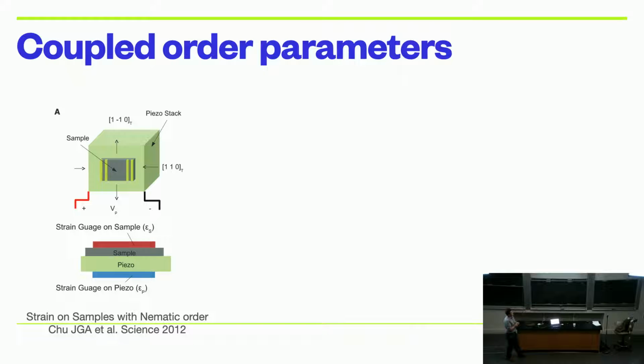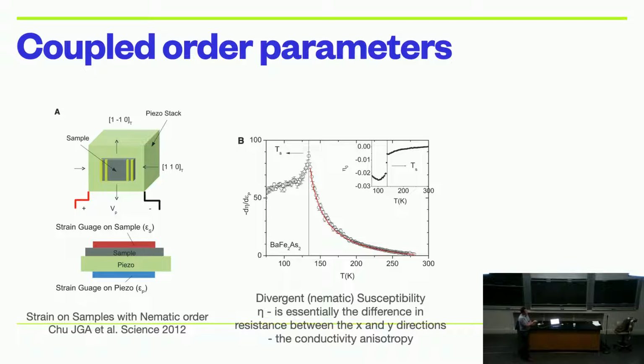So we got our crystal, we had a piezo stack. A piezo stack is just something that you apply voltage to and it squeezes and expands at will. We could measure the conductivity anisotropy, so basically the resistance of the crystal in two different directions. And you could see how that evolves as a function of temperature. And right on TC, this is where the nematic order parameter sets in, you can see the susceptibility really start to diverge, just like the susceptibility that I showed you for a ferromagnet. And that's what I mean by generalized susceptibility.